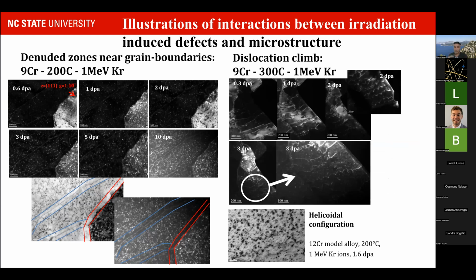Another aspect that I mentioned is the ability to look at the spatial distribution of the defects and how they interact with the microstructure features that are already there in your material. And for that matter, I could show you on the left side the effect of grain boundaries. And if there are students looking at this video, you know that in class we always mention sinks for point defects, and for instance, that grain boundaries are sinks for point defects, they're strong sinks for point defects. But what does it mean? It essentially means that whatever will form nearby can be absorbed by it, and therefore it's removed from the matrix. And oftentimes students have a hard time picturing that, and this is why I think such experiments can be very informative.